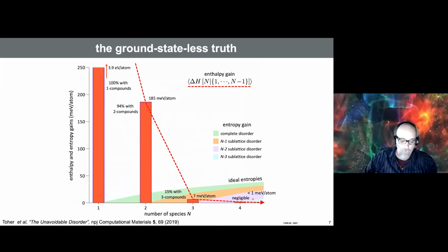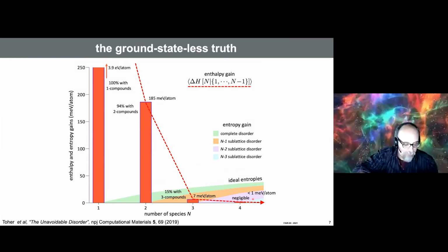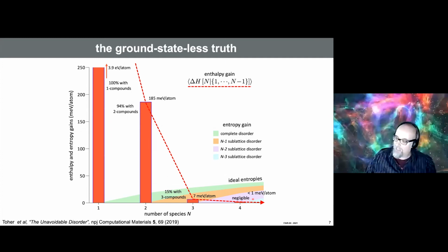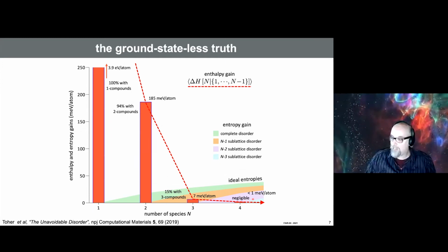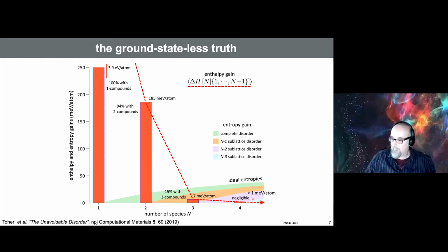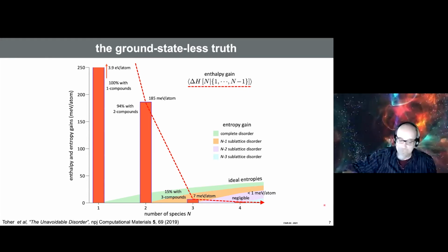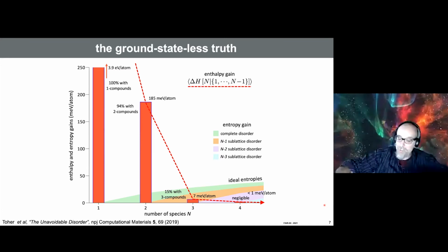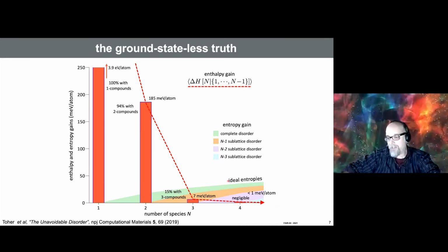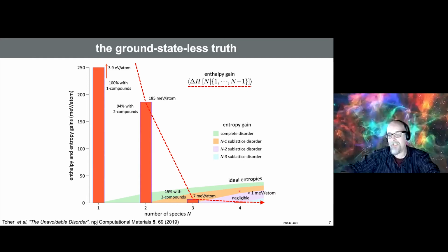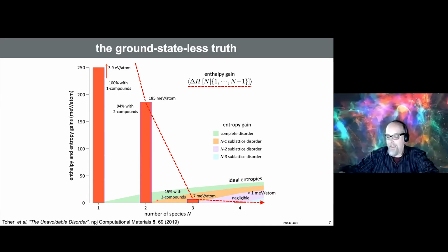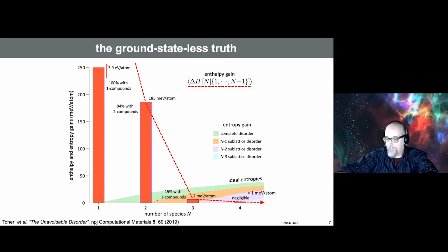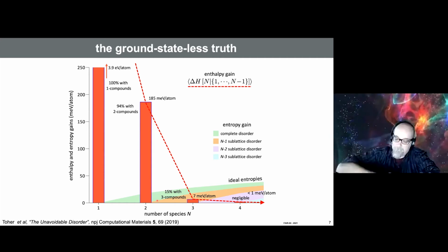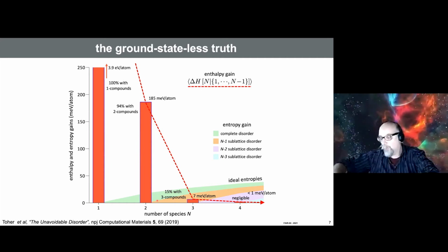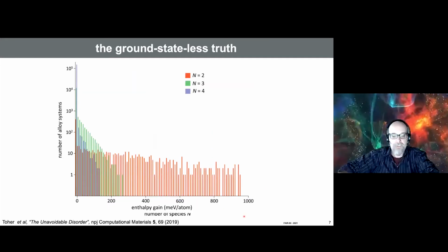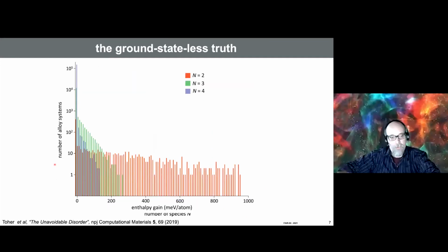So that's why if you look for Heuslers or for quaternary Heuslers in the ICSD database, most of them are actually very disordered. Okay, because at 3 and 4 species, pretty much in metals, everything is really, really disordered, right? For ceramics, we need a few species more, but the idea is the same. So this is a species-driven transition to order-disorder. Okay, so this is the flattening of the configurations.